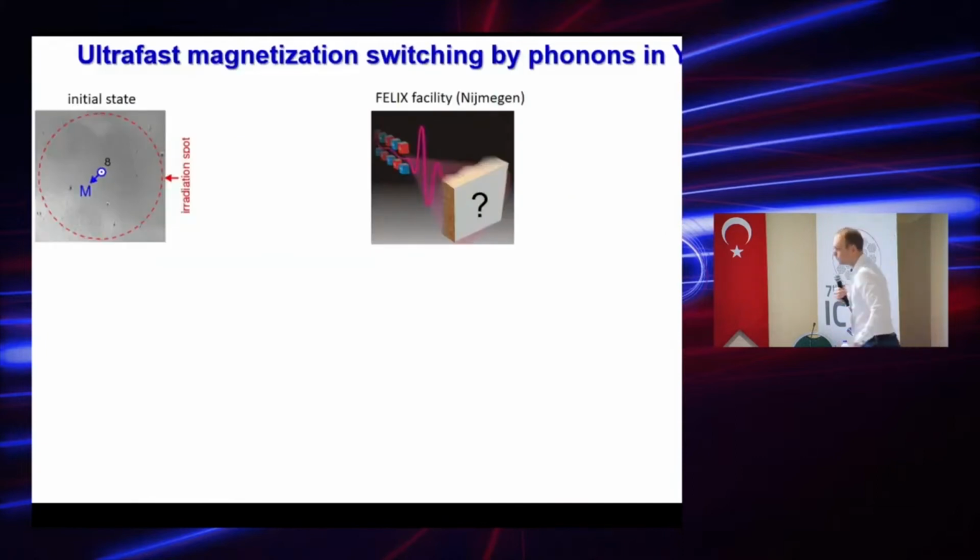Okay, in the last point of my presentation, shortly, this year we present a novel mechanism of switching. If you change the wavelength, for example, for the garnet, if you look at absorption in the garnet system, we know that wavelengths close to a few micrometers correspond to excitation of phonons. Different phonons are typical for the garnet system. If you look at 14 micrometers, we observe a novel mechanism of the switching.